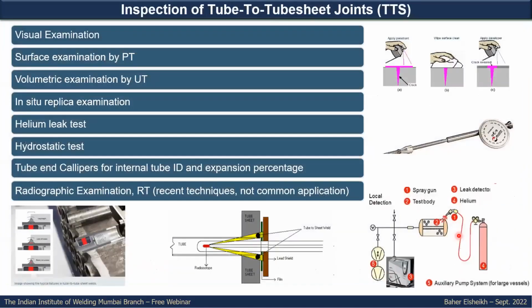Those are the most common inspection techniques we use for the tube-to-tube sheet joint, whether after or during fabrication, in-service inspection, or during repair activity. Visual examination, surface examination by PT, and volumetric examination by UT. This technique is limited to some configurations and is not commonly used. In situ replica can be applied, but it is also challenging because you might not have enough landing area on the weld to apply the replica.